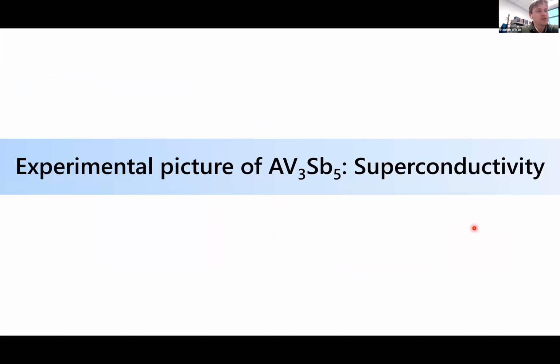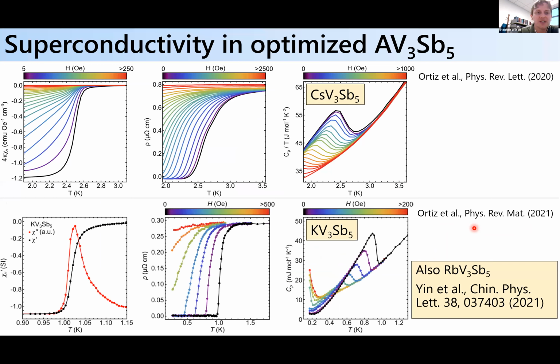Okay, so if you look at even lower temperatures in these systems, then as I've already mentioned at the beginning, the systems were found to be superconductors. This is a discovery Brenden made, reported last year, that basically the superconductivity was missed earlier because of the deficiency on the alkali site. So if you really make these things stoichiometric, then you can stabilize a superconducting state. It was originally reported in the cesium system and has a TC of about 2.5 Kelvin or so.